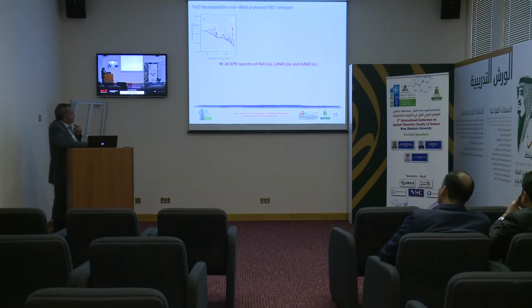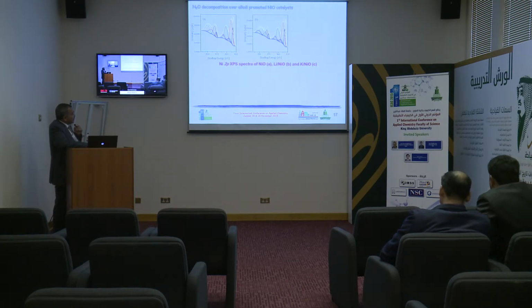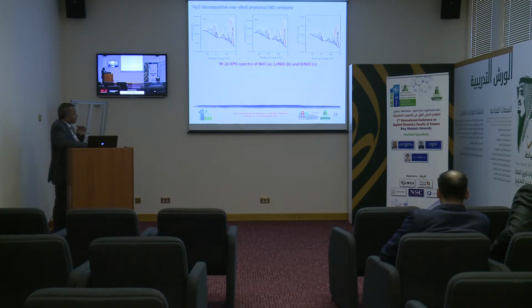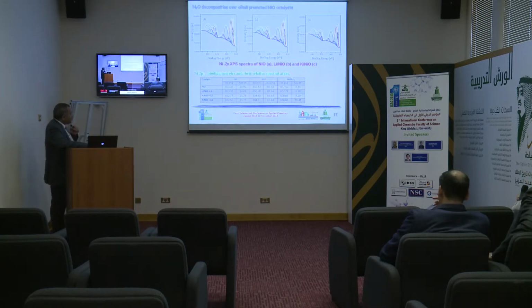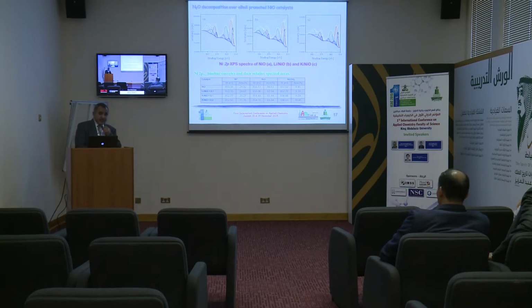Also, the same patterns can be obtained for the samples containing lithium and potassium as dopants. On analyzing these data, we can see that the 3 sub-peaks can be attributed to the presence of nickel 0, nickel oxide, nickel +2, and nickel hydroxide, also nickel +2.